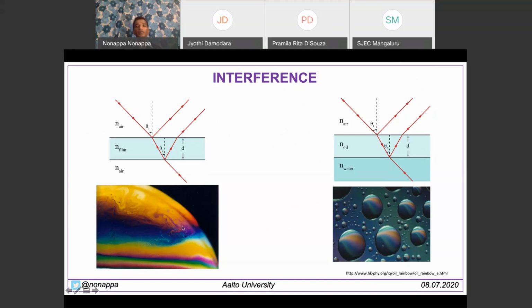Here is an example of soap bubble and oil. In a soap bubble, we have a thin air, then we have a film, which is of course a surfactant and water, and then we have air. So the light essentially goes through three different media: low, high, low. Oil bubbles or emulsion, it's also exactly the same. You have air and then your oil. Oil has a higher refractive index than water. So irrespective of the three different materials, the concept here is the same: low, high, low. So essentially we see a similar color pattern.